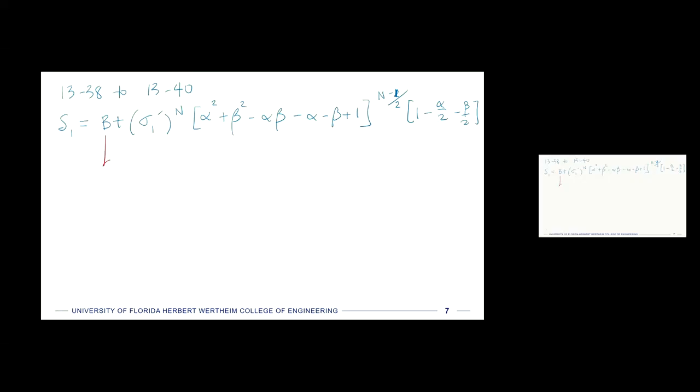So B, this is a coefficient for the log-log stress time creep law. We had B and we had N that we could describe that creep with. So N also comes from that. So I'm going to draw an arrow from here and also from here. Okay, so all those exponents are going to come from basically a lookup table, and that coefficient B for this nichrome steel at 850 degrees Fahrenheit.